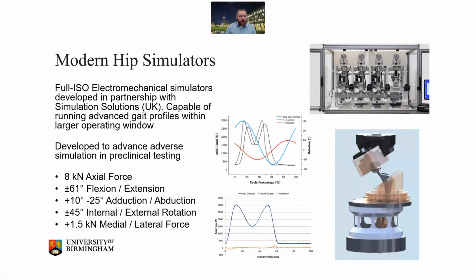So we started that by developing a modern hip simulator platform. This was done as part of an EU Framework 7 grant at the University of Leeds in collaboration with ProSim. So we developed a full ISO electromechanical simulator, which you can see swinging around there at the top right. The reason that we went fully electromechanical is that previously simulators would typically use either a pneumatic or a hydraulic loading system to apply things like axial force. Particularly with pneumatic, that would result in a delay or a lag around your desired input force compared to the outputs, and often you would have to go through an additional stage to retune those inputs to provide the output that you needed.